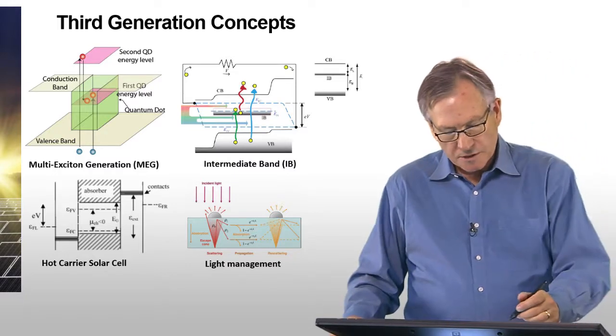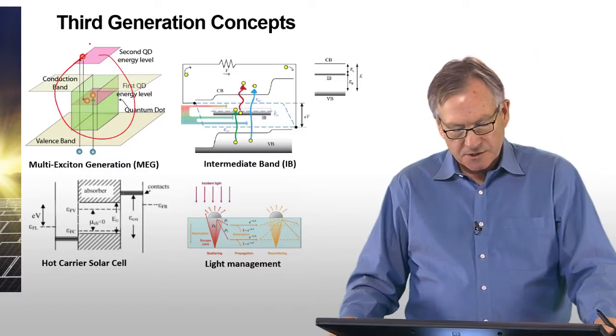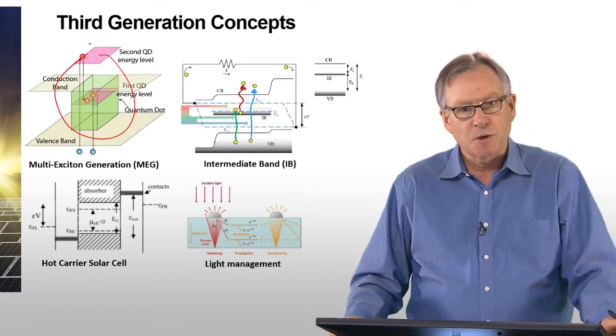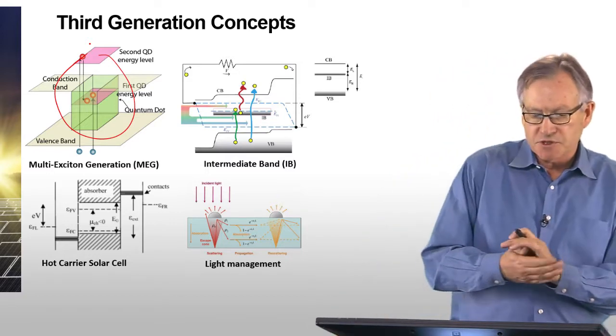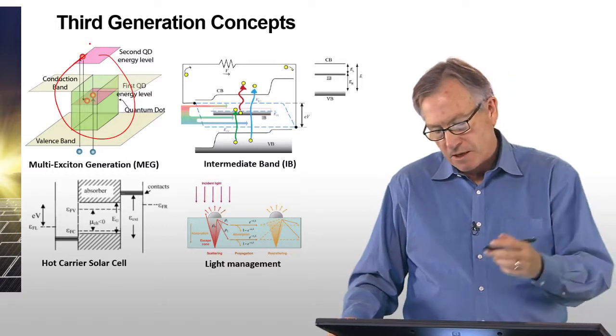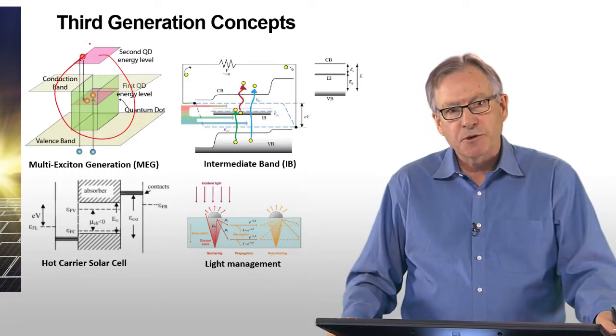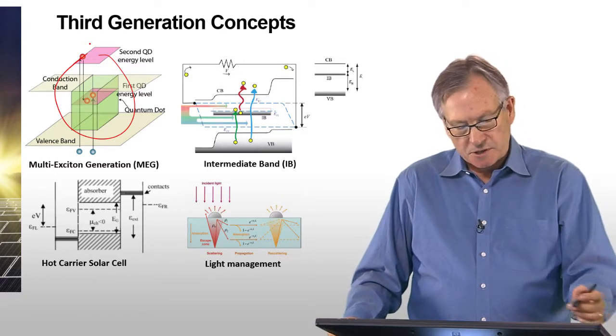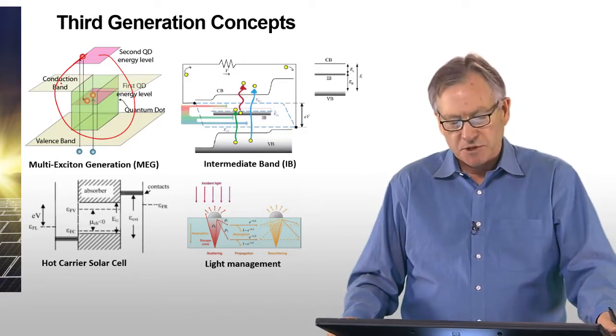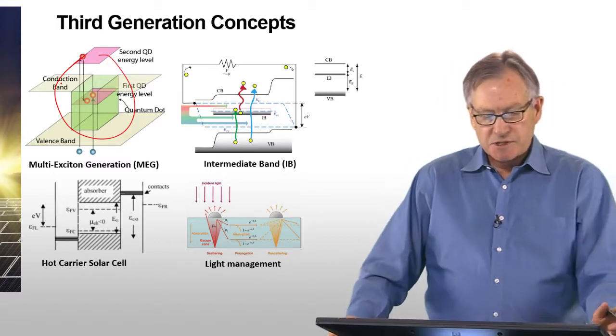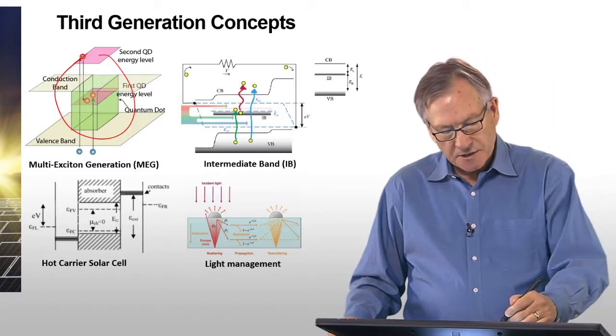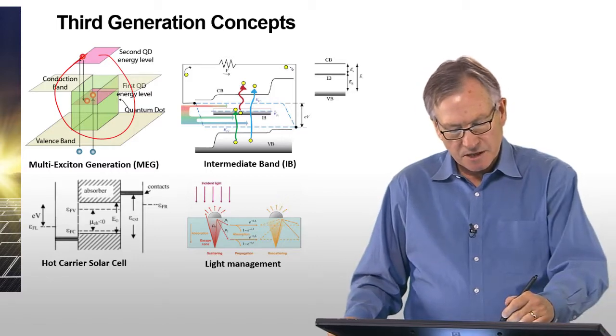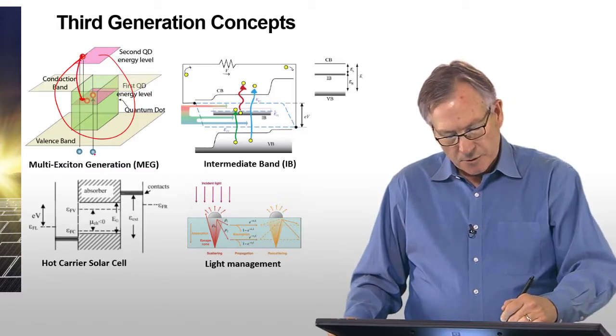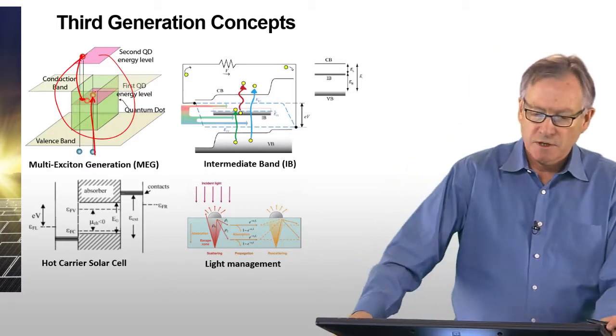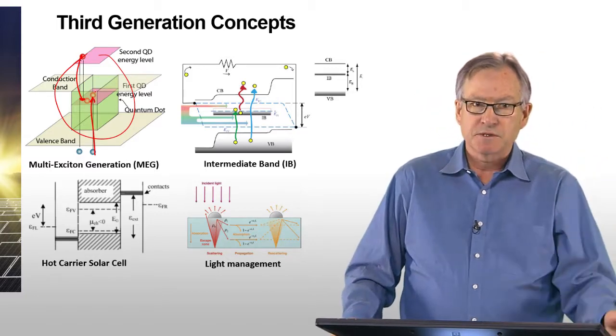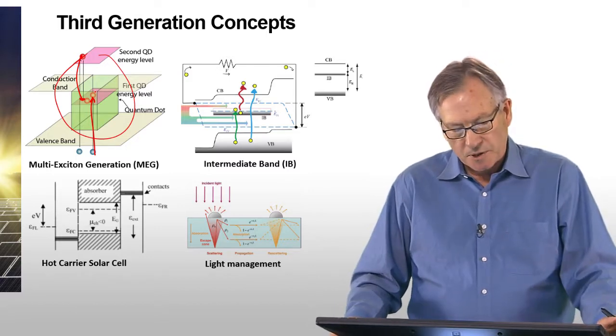So the first one is what I call multi-exciton generation, or sometimes multi-electron generation, or impact ionization. The idea simply is that you have an absorber, and it can be a solar cell material, or more frequently, what's called a quantum dot, which is a nanostructured type of material, which I'll talk about. When you excite an electron from the valence band to the conduction band, it has enough energy in this level to fall down and create a second electron hole pair. This is a process that's often referred to as impact ionization or inverse Auger recombination.